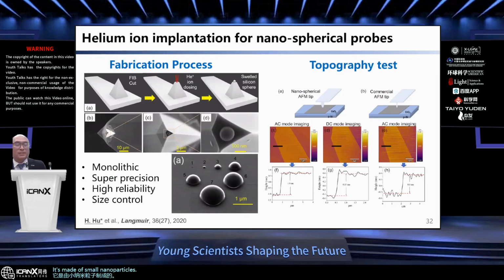So I invented a method using focused helium ions, by accident. I found out these helium ions can implant and penetrate through the single crystal silicon lattice and swell the silicon. So we can swell the silicon exactly where I want it.